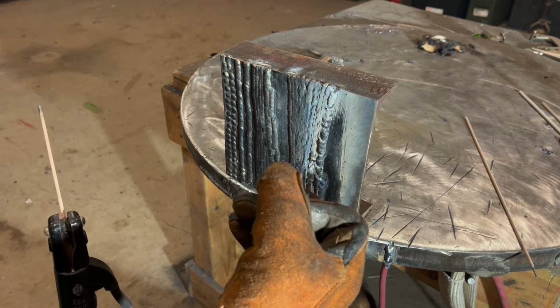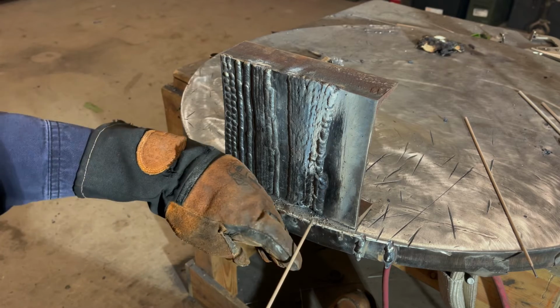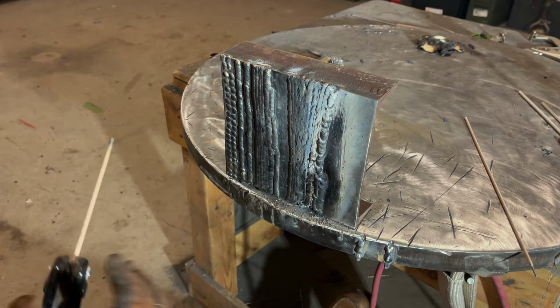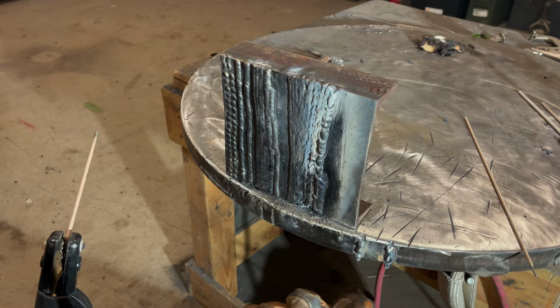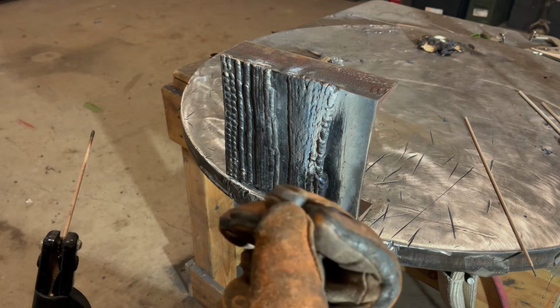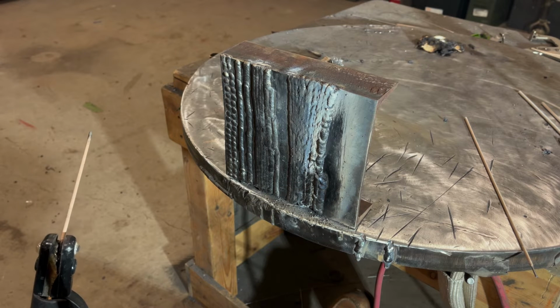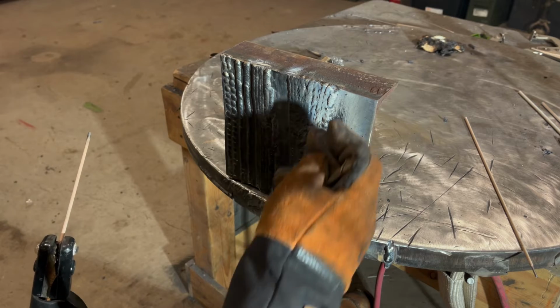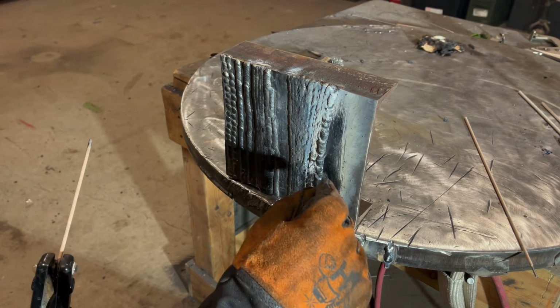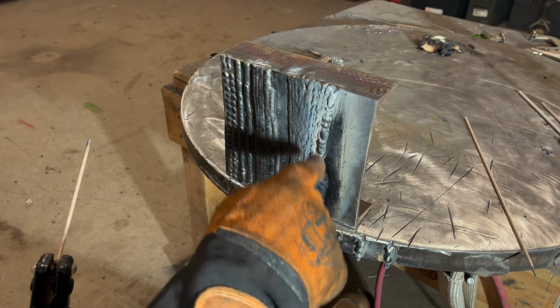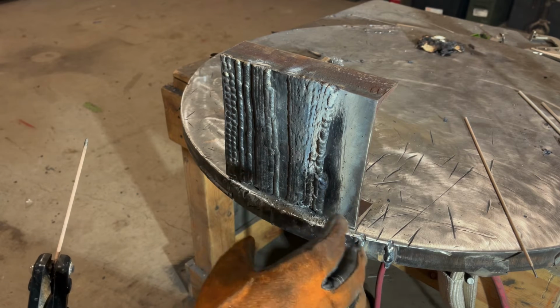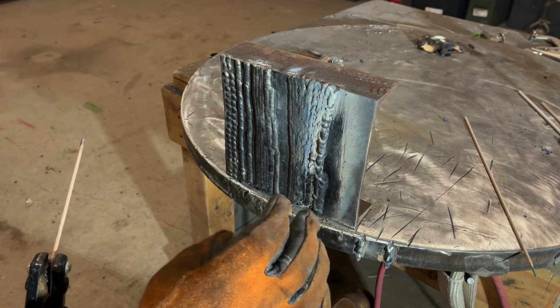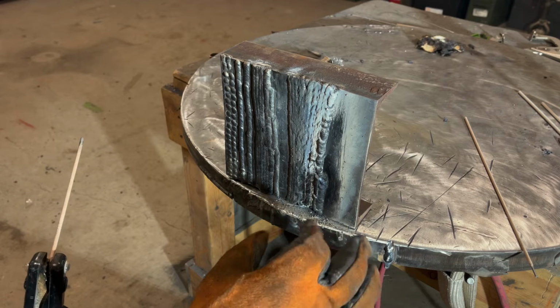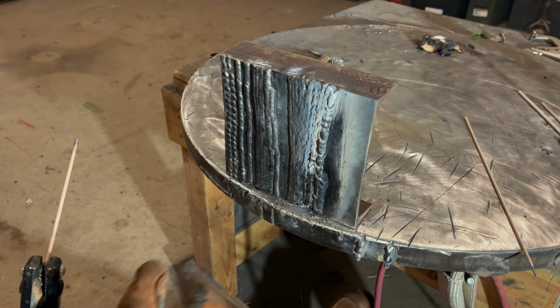Now, when you just run 6013 straight in, I find that the metal's almost too liquidy, doesn't have anything to cling to, and just has a tendency to fall down. And then you get very inconsistent height beads. So a slight manipulation in an upside down T seems to really help it flatten out a little bit. And we're talking minuscule amounts. So let's take a look at what I'm talking about.